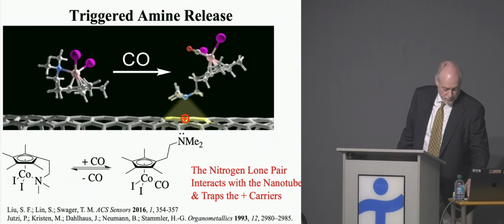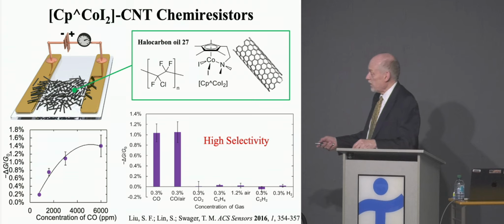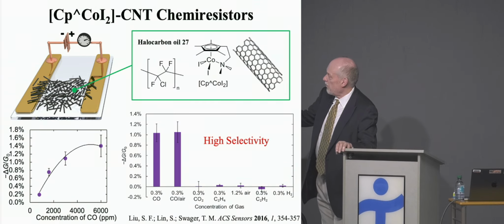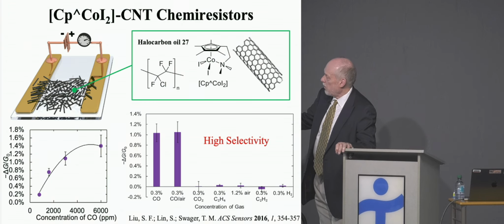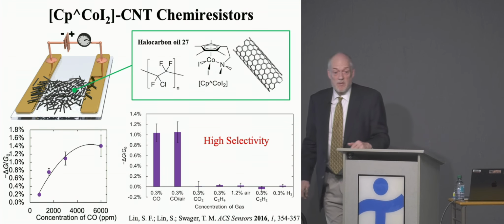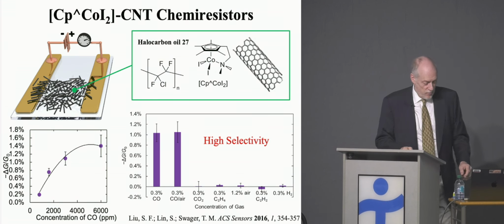And so you can do this, and we put this in a fluorocarbon solvent, or a chlorofluorocarbon solvent, to basically get rid of a humidity effect. But we just dissolve this in it, and then whambo, we get this response. And you can see it only responds to carbon monoxide, nothing else. So very, very selective because we could use it with the chemistry.